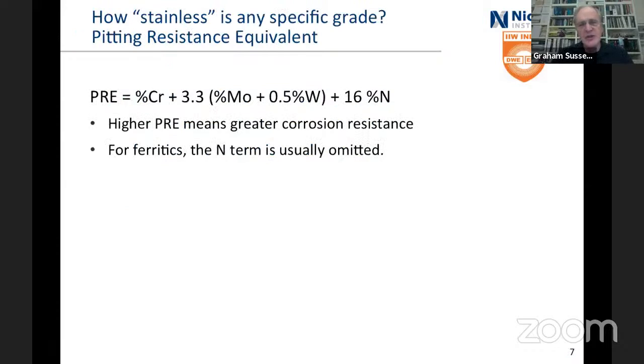How good is the corrosion resistance of duplexes and in fact all stainless steels? This pitting resistance equivalent formula has been around for 40 years or so. Look at the chromium composition, add 3.3 times the molybdenum, plus half of 3.3 times the tungsten if it's been added, and then add 16 times the nitrogen. Remember I said that nitrogen is very important for duplex stainless steels, and here is part of the reason. So the higher that number is, the better the corrosion resistance. Ferritics, well, nitrogen doesn't dissolve very well in ferritics, so usually that term is omitted, but for the duplexes, we leave it in.